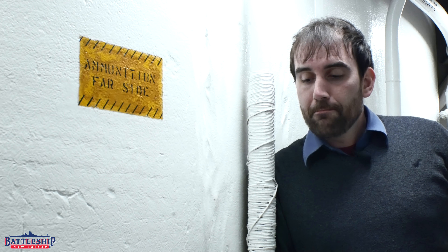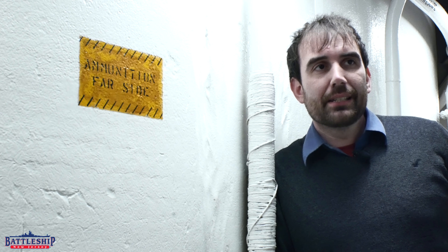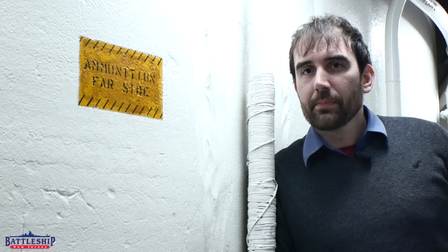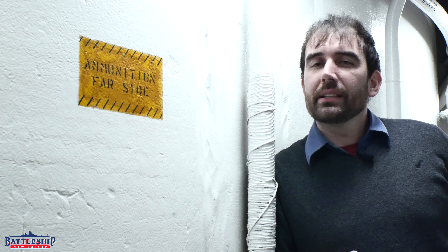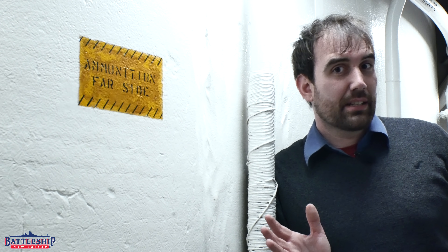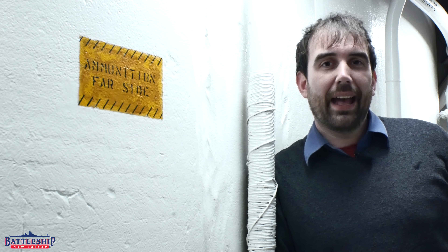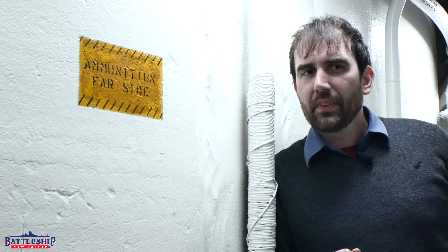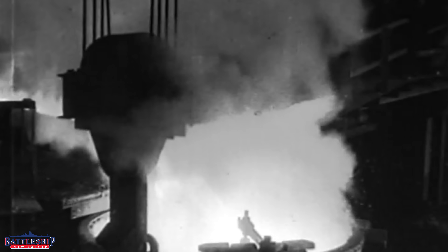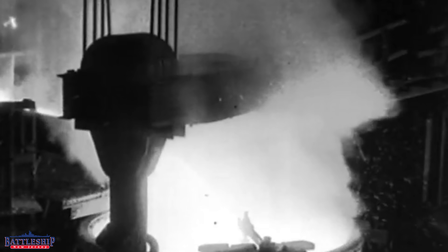The scarring also depends on the size of the armor plate and the material. If the armor is about six inches or smaller, you can roll it out, and rolled armor tends to come out pretty smooth. But if it's thicker than six inches, usually you have to cast it — especially if it's going to be face-hardened Class A armor as opposed to homogenous Class B armor. Class A face-hardened armor tends to be cast more so than Class B armor.